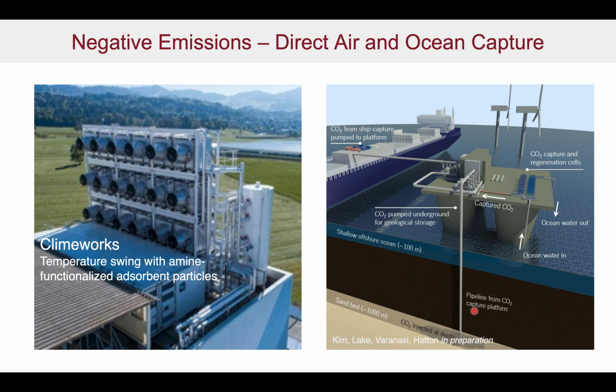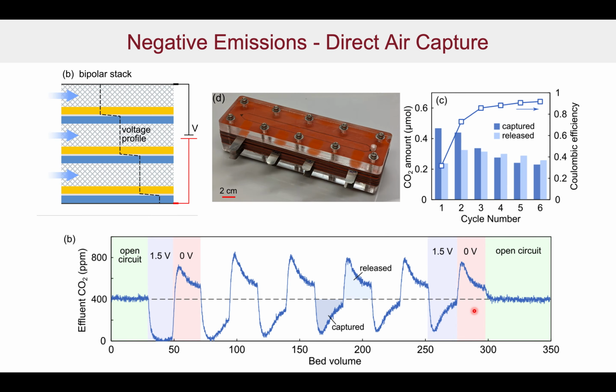We do need to think about negative emissions and look at direct air and ocean capture. From an electrochemical perspective, these are still very new topics, and so I'd like to go over some very preliminary results we've got in the system. The first is looking at the quinone system again. In this particular case, you've got the stack of cells as shown here. We flow CO2 in and have a voltage applied, and then we release the voltage and release the CO2, back and forth. So we can get the captured CO2 given by the integral under this curve, and this is the released.